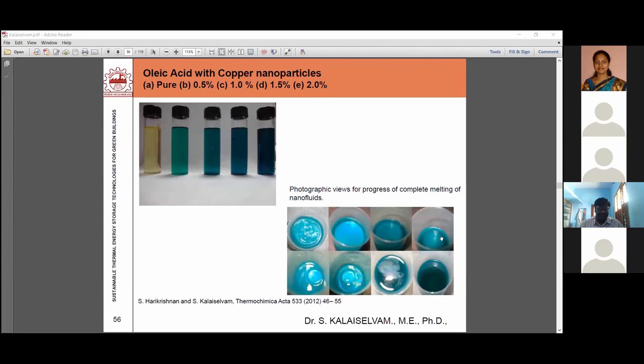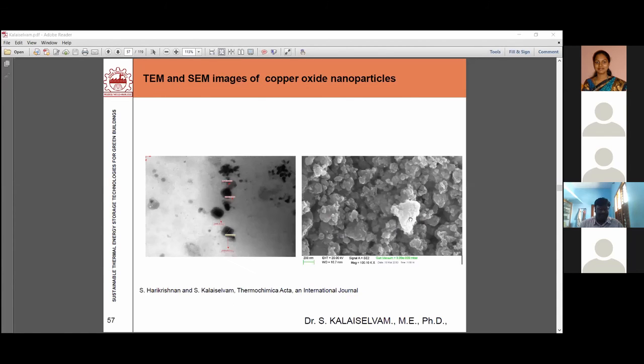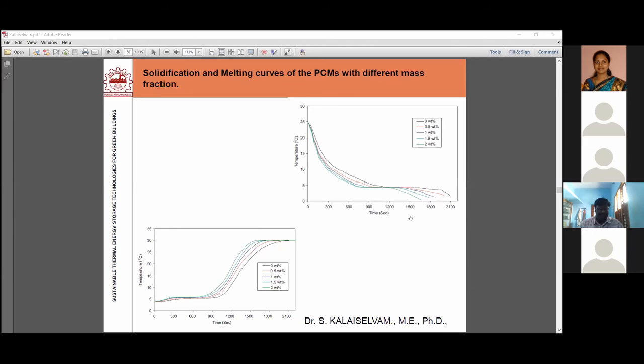And these are some of the PCM with copper oxide nanomaterial. This is oleic acid nanomaterial in a pure form, by adding 0.5%, 1%, 1.5%. And this is a photographic view of the solidification image. It was done by our researcher. This again is the image of the nanomaterial that was produced. And this again is a solidification and melting curve of the PCMs with nanomaterials.